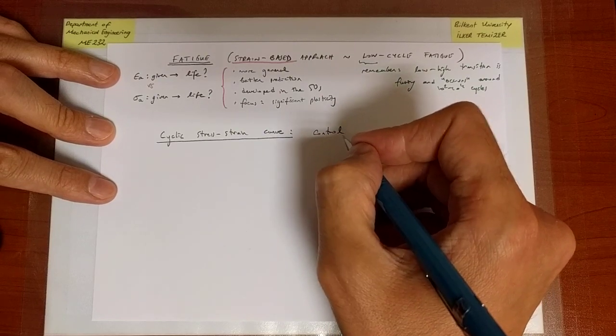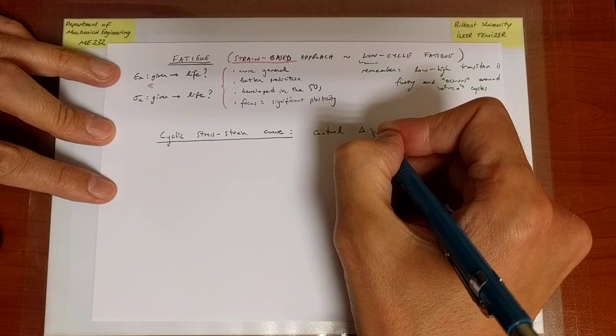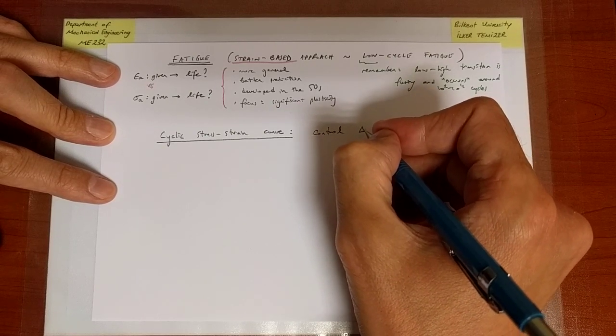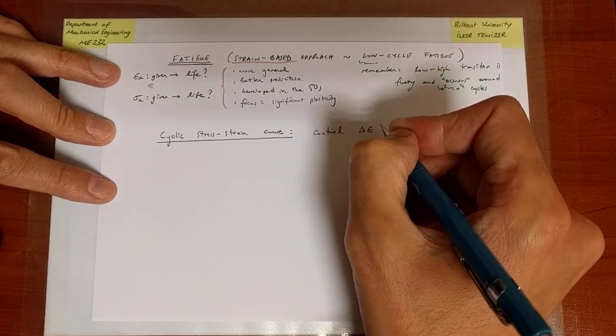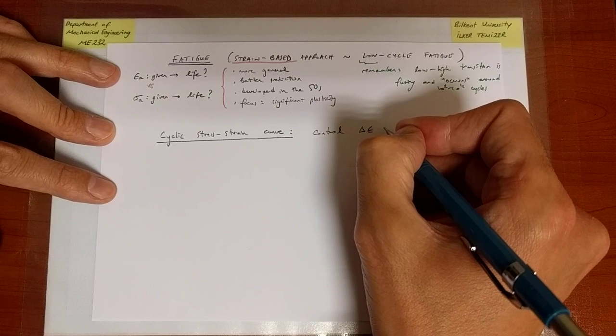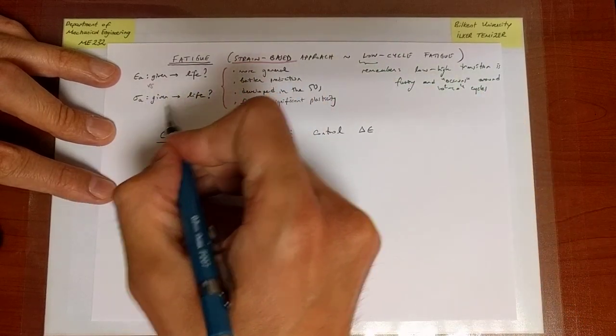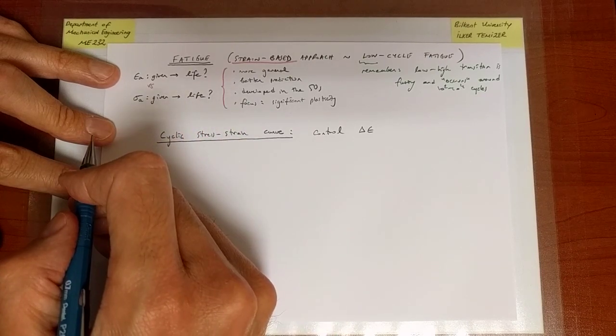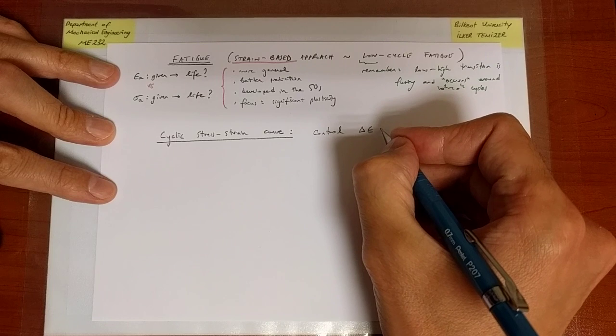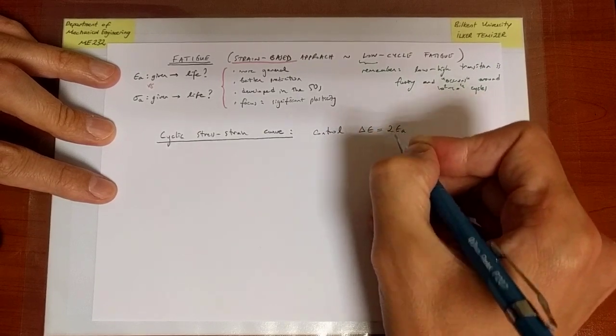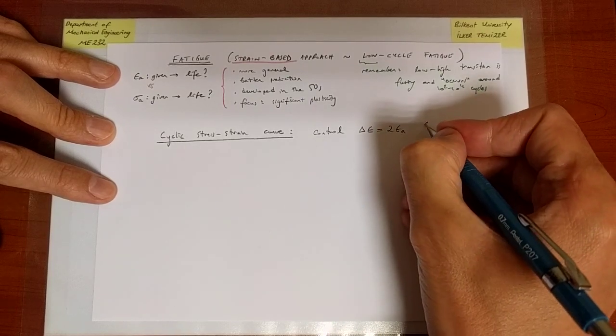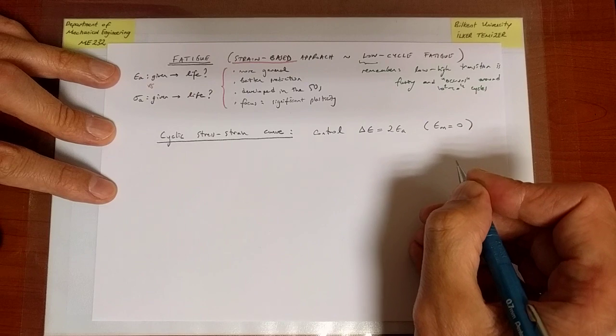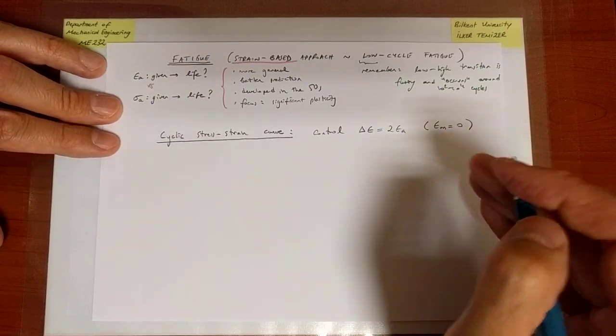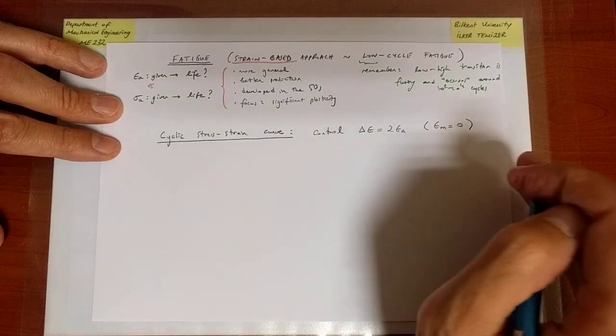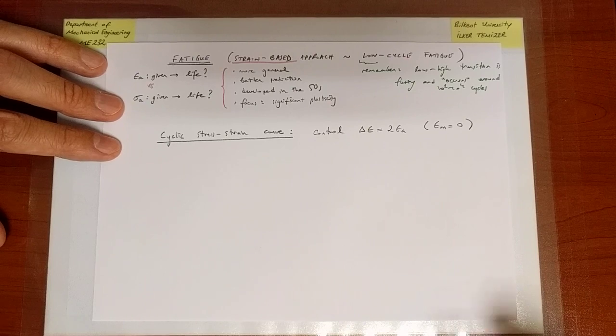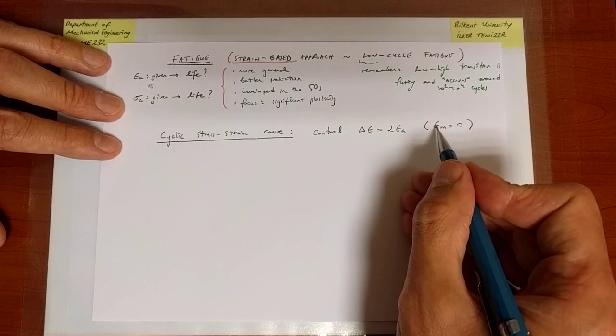Now, the idea is that we're going to carry out strain experiments, fatigue experiments in terms of strain control. So we're going to prescribe not the amplitude, or in other words, the range of the stress. That's what we would do in the stress-based approach, but rather we're going to prescribe the range, or for that matter, the amplitude of the strain. So the range is twice the amplitude. Remember when we started discussing the stress-based approach, the basic Basquin equation, we assumed one dimension, normal stresses, and no stress concentration, no mean stress. So presently we're going to assume that there is no mean strain, there is only one strain, and there is no notch, and that strain is the normal strain.